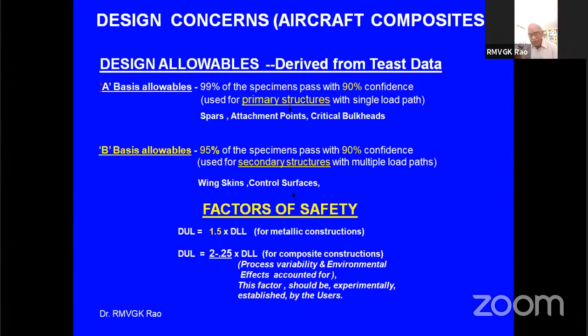That means in case of metallic or brittle materials, metallic structures, they initially follow the Hookean elastic curve, and then slowly they yield, that is sigma y. That yield point, DLL, you multiply it by 1.5, so that at that you test it. But when it comes to the composites, like polymer fiber composites, you use something like a 2.25. That means here the design limit load is a failure. That is, it goes like a brittle material, straight line, it cracks, because composites are brittle. They don't deform by plastic deformation. They don't have a yield.